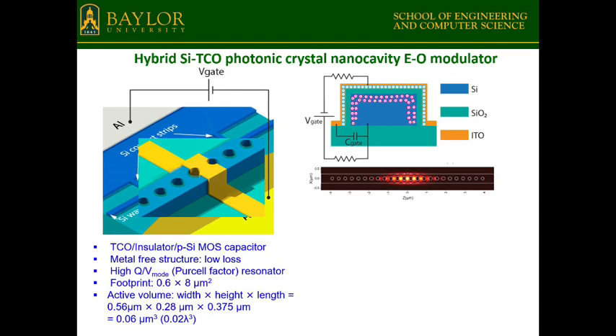The advantage is this structure is extremely compact. If you're comparing with the cavity, the volume of this region is only about 2% of the wavelength cubed, or the length of this structure is only like half a micron. But if you're comparing with a traditional electro-optical modulator, it's probably hundreds of microns. So basically, you greatly reduce the size of the electro-optical modulator. And why do you need to do that? If you're considering the energy efficiency of your transistor, make it smaller, it will be more energy efficient. So it's the same way here.